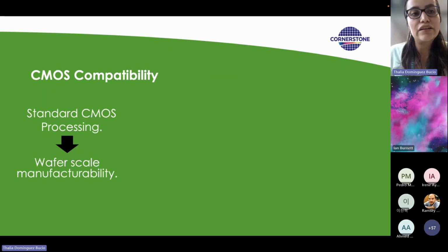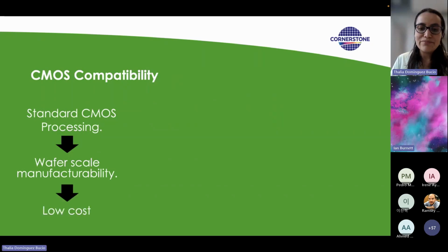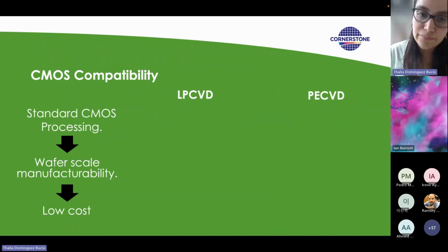We can fabricate silicon nitride devices on 8-inch wafers, 12-inch wafers, compared to other materials that are also around in the integrated photonic community that can only be fabricated in very small wafers, which means overall that we can fabricate these devices at a low cost.